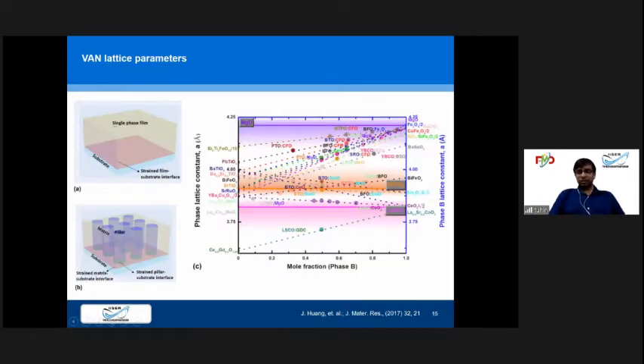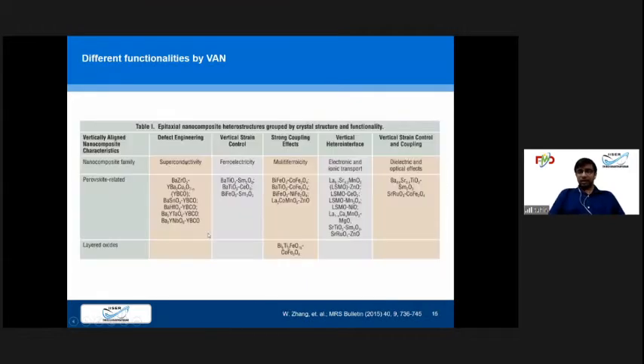If we have a normal single phase film without any column, only the region near the substrate is strained and the rest of the film does not feel the substrate, so there is not much control over its functionality. But if we create a vertically aligned nanocomposite, then we can change that. There is different research going on to make this kind of vertically aligned nanocomposite. But by correctly choosing the substrate and the material compositions, we can rightfully choose the amount of strain and create the right amount of pressure. So this is another material which you can use, so the composition we have to consider.